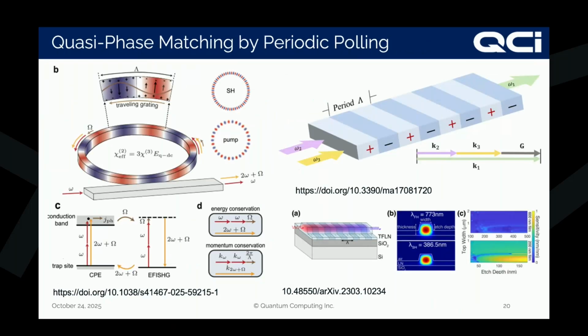Another feature special to thin film lithium niobate, and materials with large Chi2 and Chi3 nonlinearity, is having the periodically poled lithium niobate structures. So with PPLNs, we can do phase matching in a way to be able to combine two photons in a nonlinear format that have frequencies of, let's say, omega 2 and omega 3. And then the output when the light propagates through this waveguide would be a photon with frequency omega 1, which equals omega 2 plus omega 3. So you can do up conversion and down conversion in such materials. And that's what you can see theoretically depicted in here.